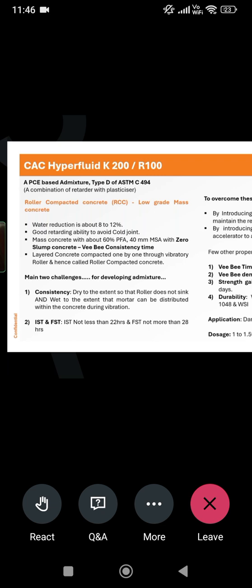There are two main challenges for developing this admixture. One is consistency: dry to the extent that the roller does not sink, and wet to the extent that mortar can distribute within the concrete during vibration. It's very difficult to achieve this kind of consistency. Too many trials are required.